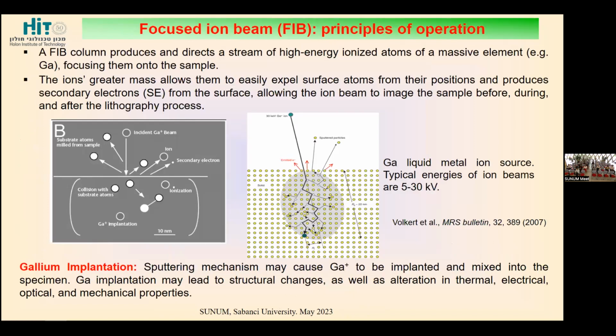Yeah, here are a few words. People from this subject know much more than me. But here is the mechanism of gallium implantation through a number of processes. Generally, energies of 5 to 30 kilovolts of ion beams are used. And because gallium is quite a heavy atom, it can both release some other materials and also be implanted inside. This process of gallium implantation is of our interest.